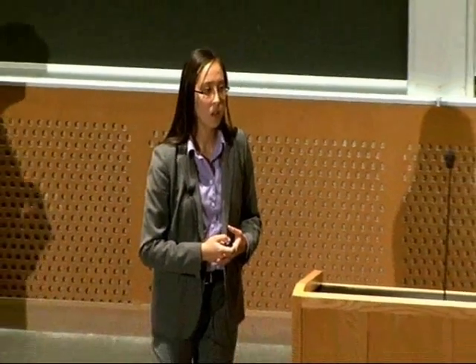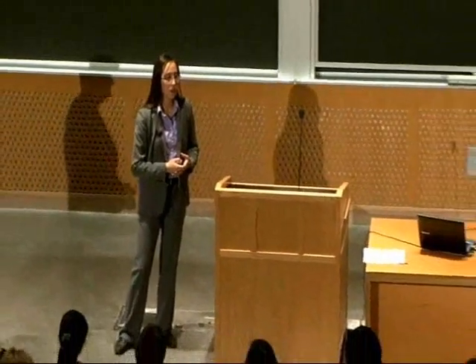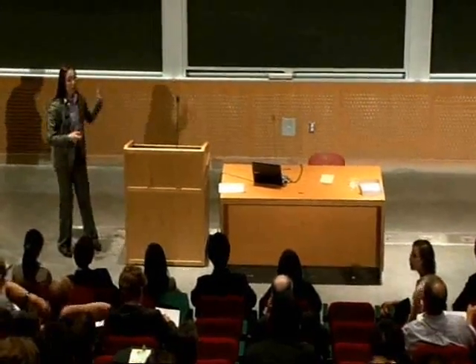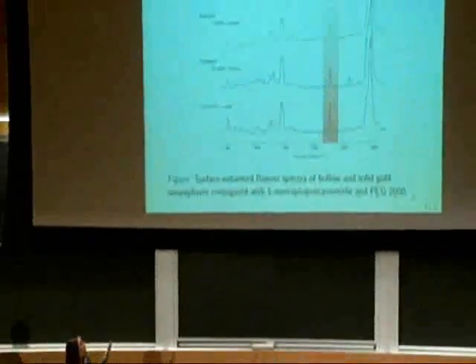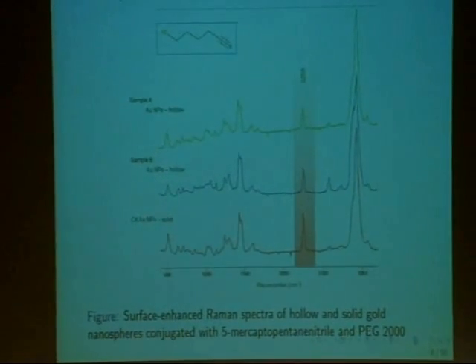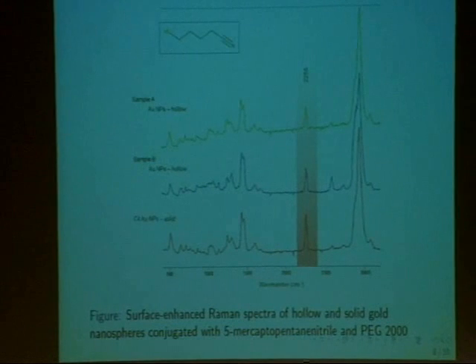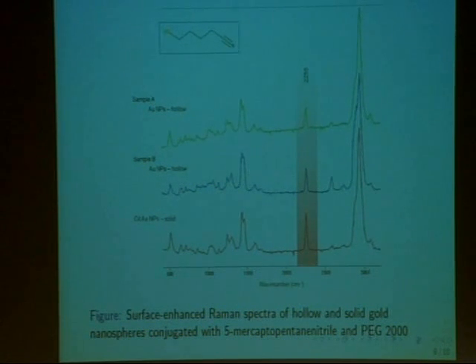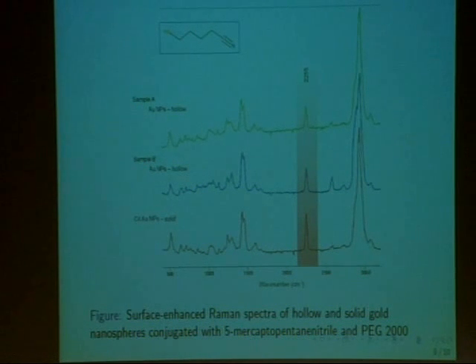Question: Was there an intermediate step performed where you checked the success of the nitrile functionalization? Yes — the Raman spectrum of the nanoparticles outside of cells was that intermediate step. You can see they do have a nitrile stretching peak. This is probably not due to any free nitrile groups, because the nanoparticles were purified before imaging. So it's likely that the peak is associated with the nanoparticles. Let's thank Deborah.